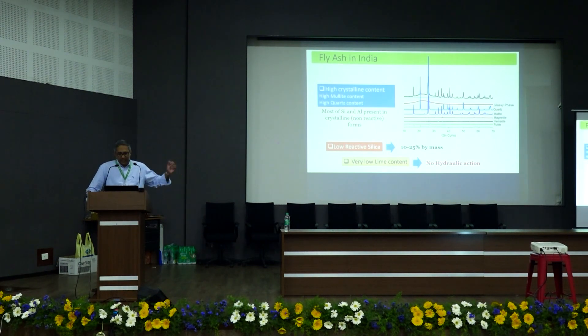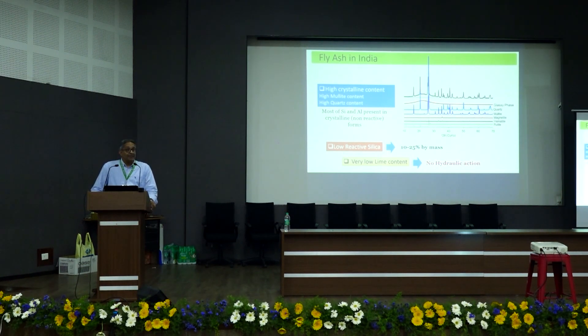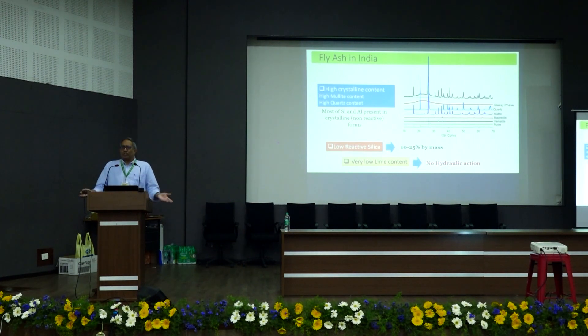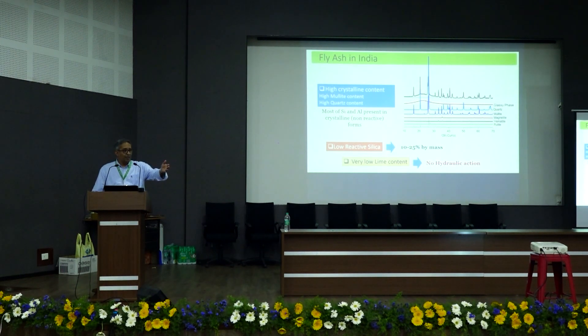In the X-ray diffractogram, the black line shows the overall XRD signature. There's a hump from a 2-theta angle of about 20 to 30 degrees — that is the reactive part, the glassy spheres, the reactive silica present in fly ash. After decomposition of this signature, the glassy portion — shown as the orange line — is what I need to leach out. What's left behind is quartz, mullite, and basically all inert material. Quartz is sand. So I take fly ash, leach out silica, give you nano silica in a highly reactive form, and what I leave behind is sand for use as fine aggregate. Win-win.